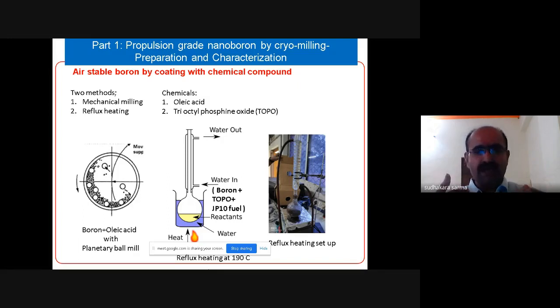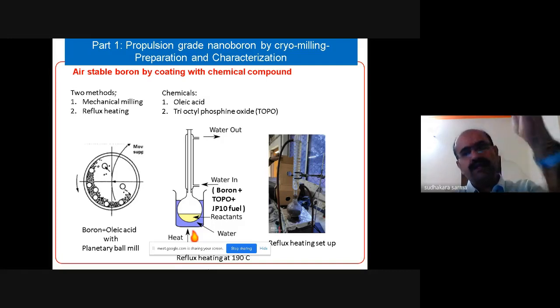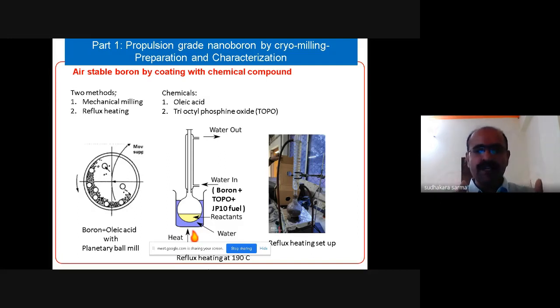And another technique is reflux heating. In reflux heating, we mixed the boron powder into the JP10 fuel. We also added 0.1% of TOPO, trioctyl phosphine oxide, and then heated up to 190 degrees centigrade. While heating, the oil evaporates and again condenses at the condenser. Condensed oil comes down, and like that the heating takes place, and after 6 hours of heating, enough TOPO is coated onto the boron, and I will show you.